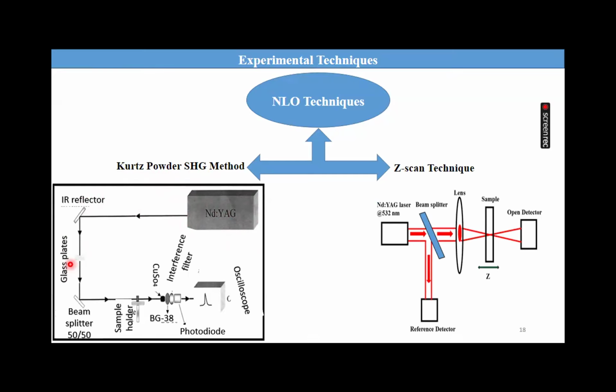The output of the Nd:YAG laser, neodymium doped yttrium aluminum garnet, can be used to investigate the sample's nonlinear optical behavior as it passes through the crystalline powder. About 6 millijoule pulses of fundamental radiation at 1064 nanometer were produced using a Q-switched mode locked Nd:YAG laser.